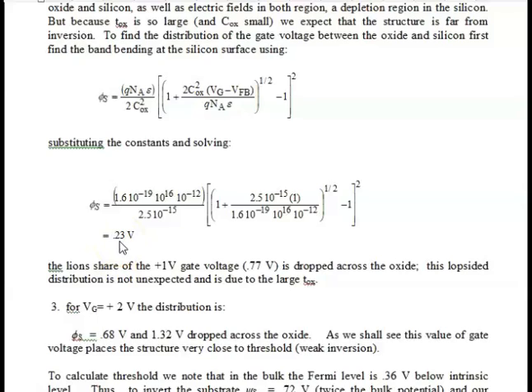It must be that the remainder of that 1 volt is dropped across the oxide, and of course that makes sense. Now, why is more voltage dropped across the oxide than across the silicon? And the reason is the oxide thickness, T-ox, is very large. And that's what we expect. If we had a smaller oxide thickness, we would expect these numbers to be reversed. We would expect more voltage to be dropped across the silicon and less to be dropped across the oxide.